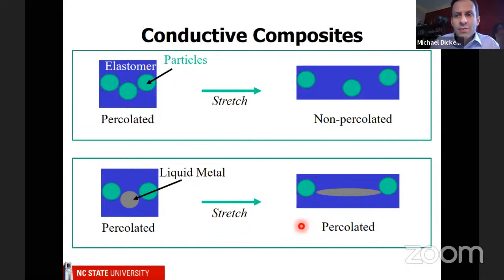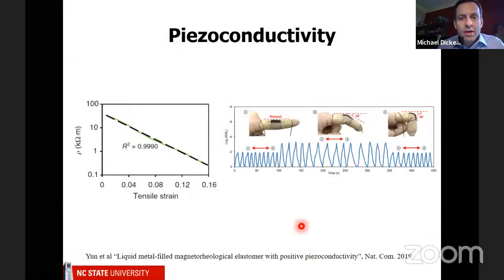But what was really weird, and honestly, we don't understand this fully, but if you measure the resistivity as a function of strain, you get enormous changes in resistance. So this means the material is getting more conductive, but look at the axis here. This is a log scale. So it goes from like 100 to 10 to 1 to 0.1. And that's only with 0.1 strain. So if I take this and stretch it like that, that's a strain of 1. 0.1 would be like this. You almost can't even see it. So with a very little strain, we're getting a huge change in conductivity.